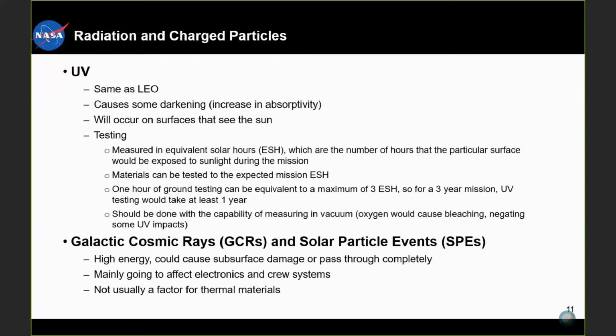So starting with UV, as I said before, this is the same as you'll get in LEO and GEO, because we're pretty much the same distance away from the sun, and that's a determinant in UV. So UV can cause darkening on surfaces, so an increase in absorptivity, and it will occur on surfaces that see the sun. So testing for UV, we can do ground testing. It's measured in equivalent solar hours, or ESH, which are the number of hours that the particular surface would be exposed to sunlight during the mission. Materials can be tested to the expected mission ESH on the ground.